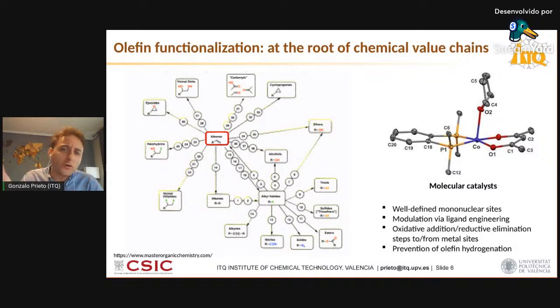These are long-optimized catalysts in the industry at present, and they are capable of driving, for instance, oxidative addition and reductive elimination steps to and from the metal center, which are typically key in mechanisms involved in olefin functionalization. And that's an important feature of these optimized catalysts. They are also capable of inhibiting the thermodynamically most favored but less desired side reaction of olefin hydrogenation to the corresponding paraffin, because the paraffin would have a way lower added value than the starting olefin in the first place. So that's another very important feature that we should be able to mimic if we are aiming to produce analogs of this molecular catalyst, but now in solid state.